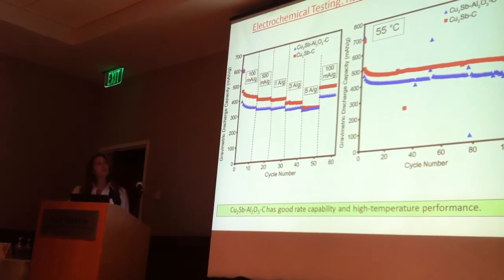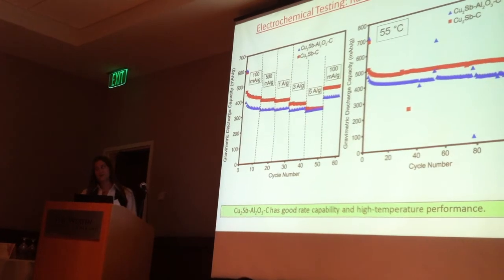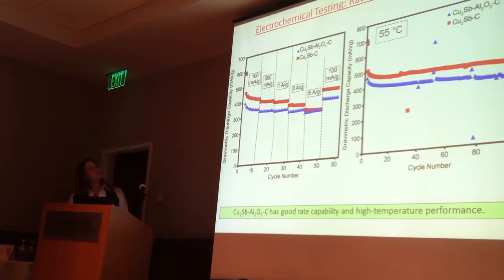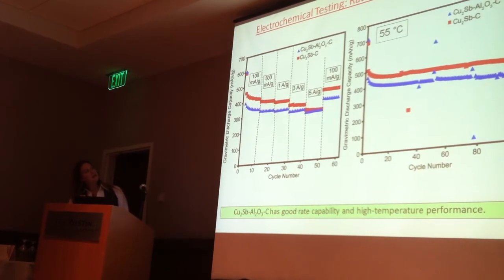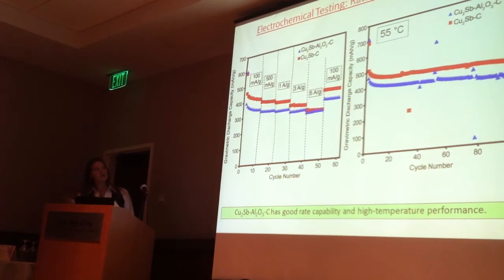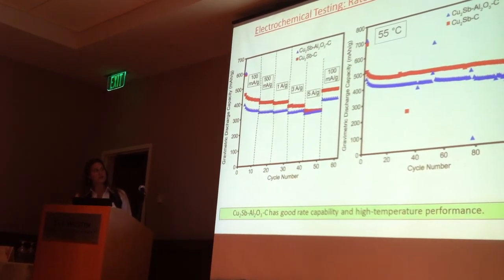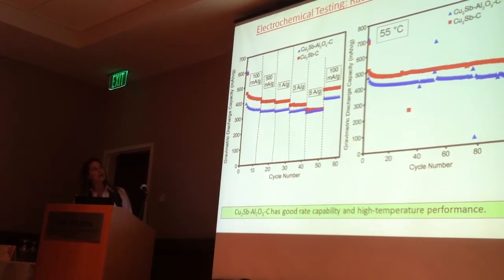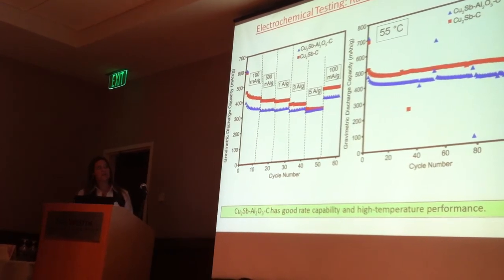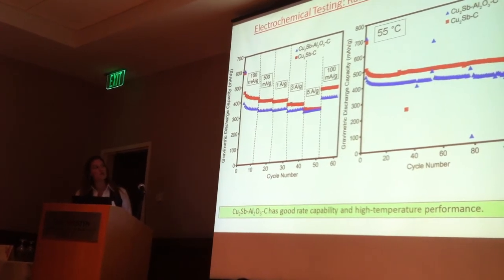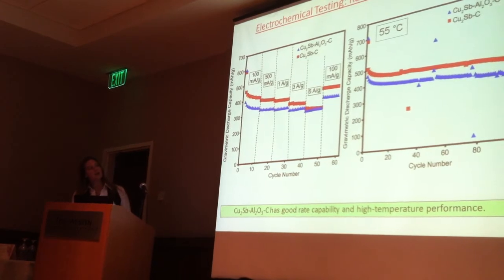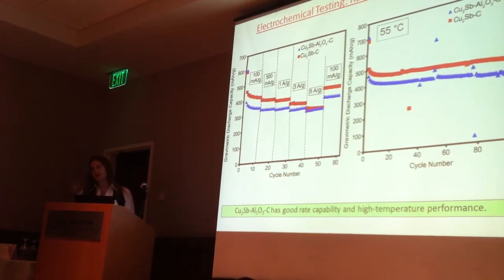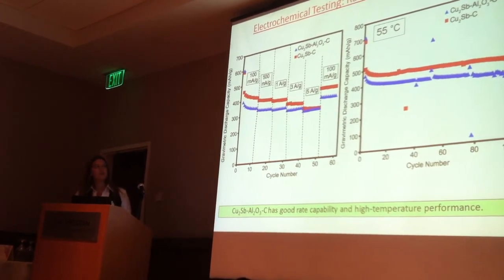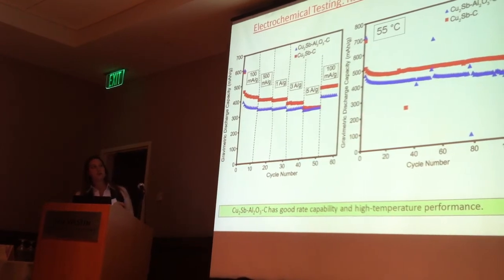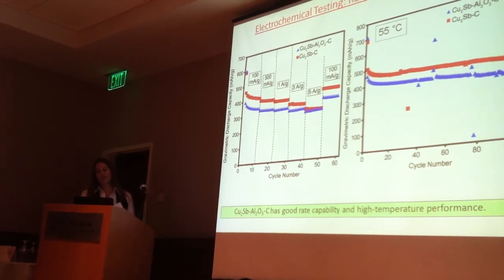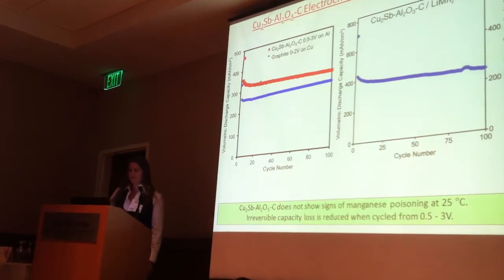We also looked at the rate capability and high temperature performance for this material. You can see that even at a charge rate as high as 5 amps per gram of composite material, we still have a gravimetric discharge capacity that's around that for commercial graphite. The high temperature performance was not as great as the room temperature performance, as you might have expected, but it was fairly stable for at least 100 cycles.